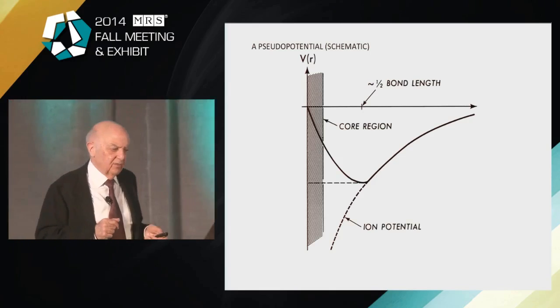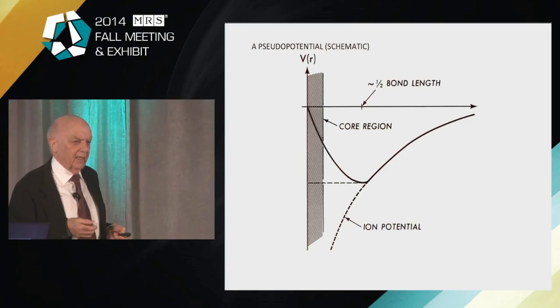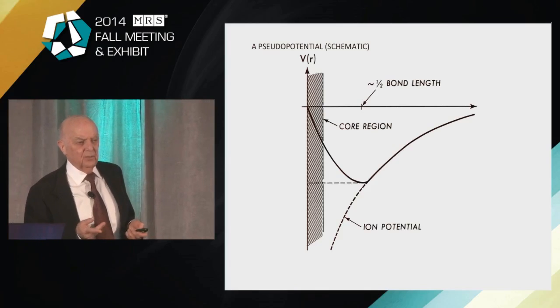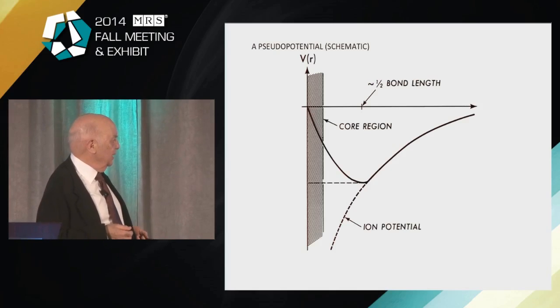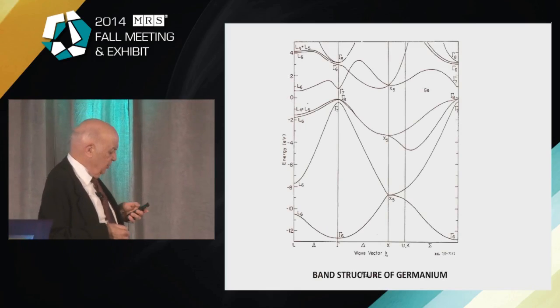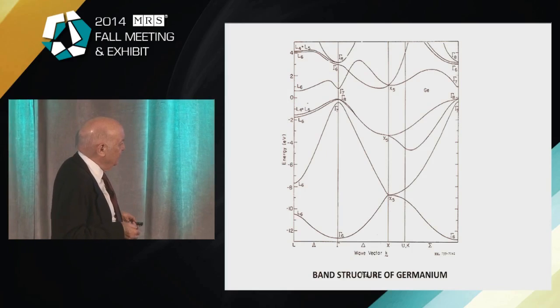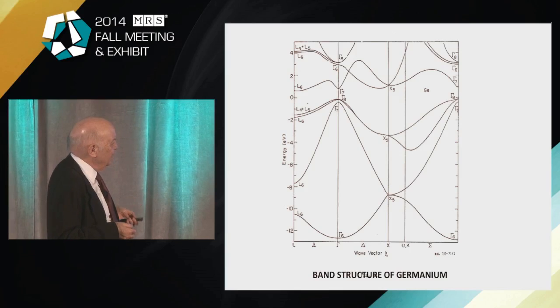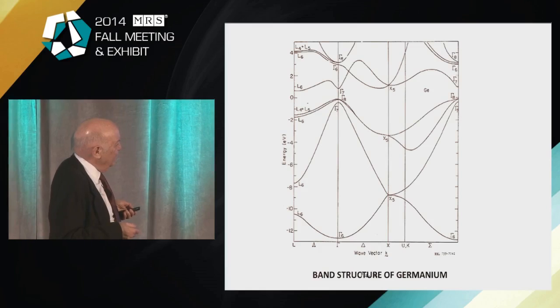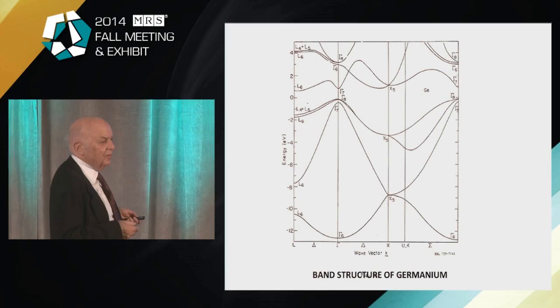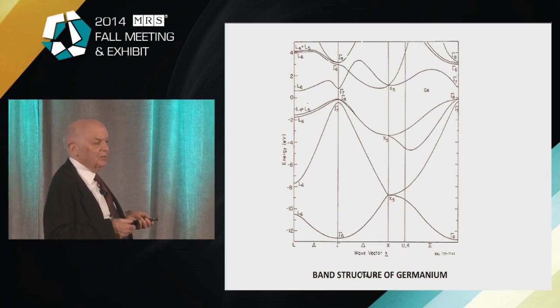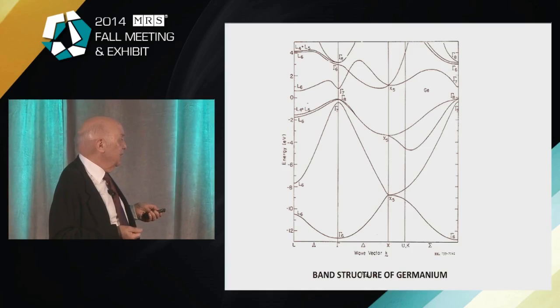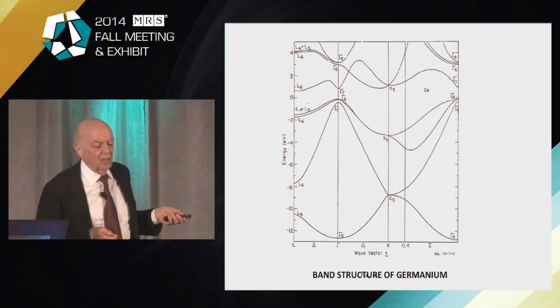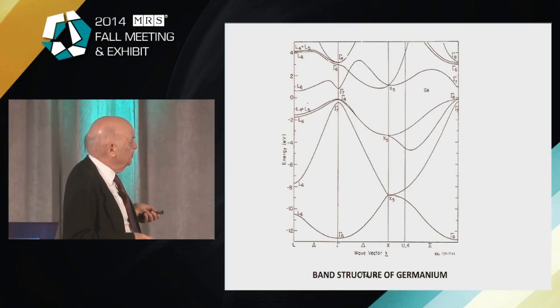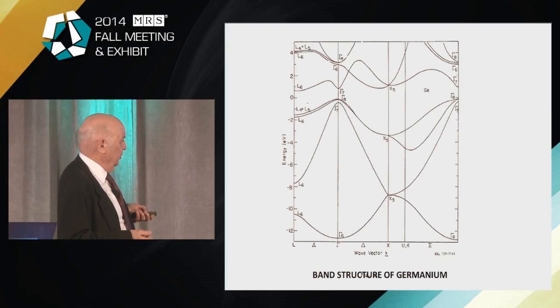And if you take the Fourier transform of that simple potential and put it in a periodic lattice for systems like diamond or silicon or germanium or tin, you only need 3 parameters to give you the electronic band structure. And this is what a real electronic band structure looks like. Before, I just had flat energy levels, but now as a function of wave vector, you see that these have detailed structure. And then the optical properties come from taking electrons from these occupied states to the empty states, and the gap is there. And this is all done with 3 parameters taken from the optical data, and explains all the properties of germanium in terms of the electronic properties and optical properties. And this was done many years ago, and it's still one of the most accurate and precise band structures available. But it has an empirical part.